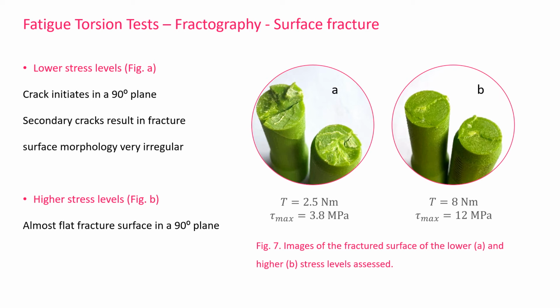longitudinal axis, but also originating secondary cracks, which results in a very irregular fracture surface morphology, as can be seen in Figure 7a. When the intensity of the load is increased, specimens tend to present a flat fracture surface, as shown in Figure 7b.